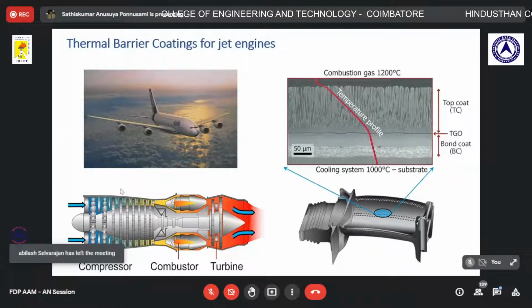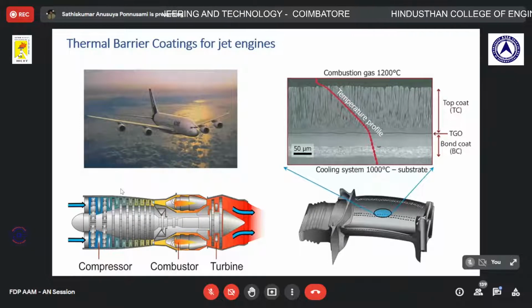Yeah, so as you can decipher from the top right image of the microstructure, you have different layers there. Yeah, it's a single coating, but it's more of a hybrid coating. So you have a blade underneath, that's the metallic blade, and on top of it you have the so-called bond coat, as you can see here, if you can see my mouse pointer. So the bond coat is a metallic layer again that is used to bond the underlying metallic blade to the ceramic coat on the top, and that ceramic coat is a top coat.